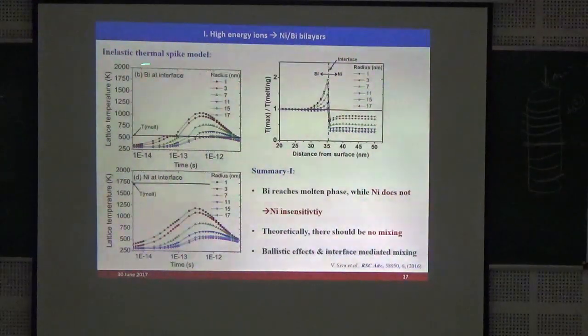So it is almost 50% enhancement in the total thickness. And we have performed realistic thermal spike model calculations in this bismuth and nickel thin films separately, and then together, keeping bismuth and nickel together. So here you can see lattice temperature as a function of time. We have drawn a horizontal line to show the melting point of bismuth, and in the case of bismuth, it is reaching melting temperature in most of the ion track radii. In the case of nickel, this is the melting point, and the lattice temperature generation is very much less than the melting point of nickel.